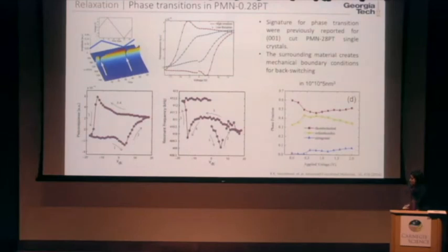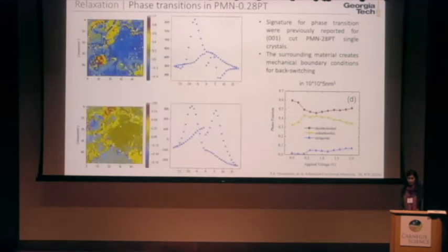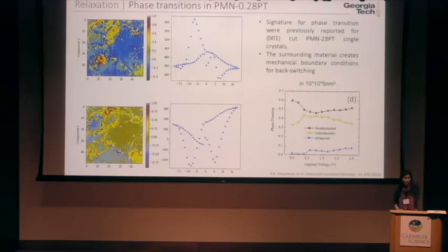So we tried to figure out what might be happening here, and because it was correlated to the very high response, we remembered our own previous work on very high response, which associated this with field-induced phase transitions. So we tried to correlate that to the switching response, and as I told you, our method does not distinguish between up and down, positive and negative, so this might seem more familiar with the butterfly hysteresis loop.